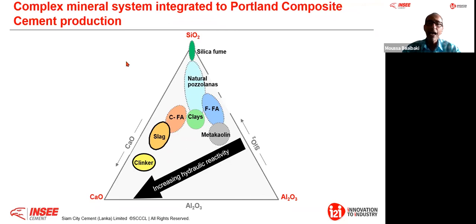However, natural pozzolan, fly ash, or silica fume are different. These are what you call aluminosilicate materials, and they need an activator. They need the lime from the hydration of the clinker to activate them. This is not like slag. Therefore, you see, this is complex because not every slag is the same slag, and not every clinker is the same clinker. Clinker depends very much on the raw material you are using to produce it, and on the process you are using. It's the same for slag.